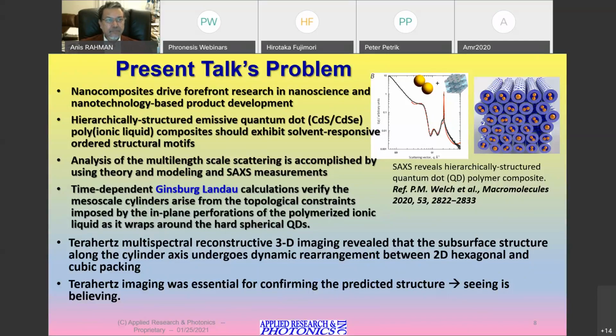However, analysis of the multi-length scale scattering was accomplished by using theory and modeling and small angle X-ray scattering measurements. Time-dependent Ginzburg-Landau calculations verify the mesoscale cylinders arise from the topological constraints imposed by the in-plane perforations of the polymerized ionic liquid as it wraps around the hard spherical quantum dots. And this is not a single wrap, it's layer after layer after layer wrapping, as we can visualize from the